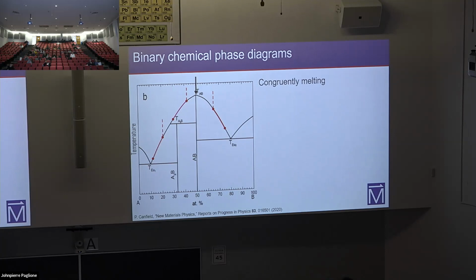And the first one is something called a congruently melting compound, or sometimes people call this a line compound. This is a compound that extends all the way up to the melt, and you have an interface between the solid phase and the melt phase. In order to access something like this, the most obvious thing to do is just combine these elements in this ratio, heat it up as high as you can, get it in the liquid state, and then drop the temperature back down. And that's straightforward.